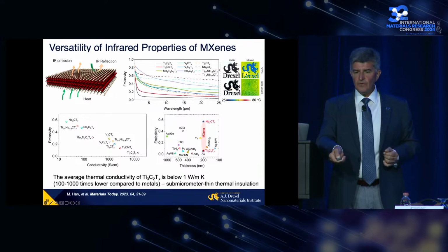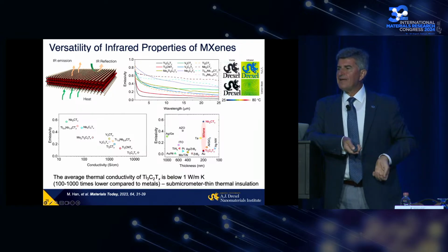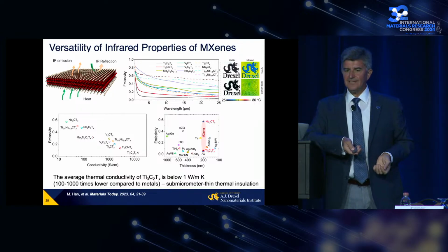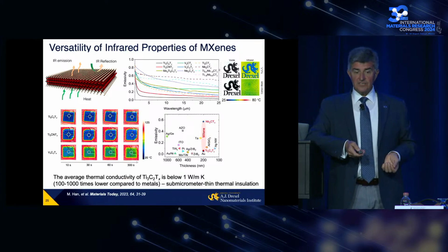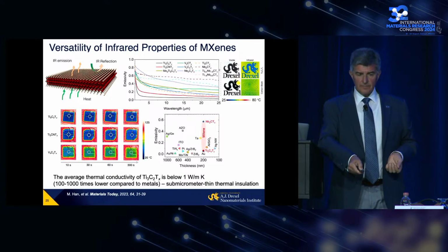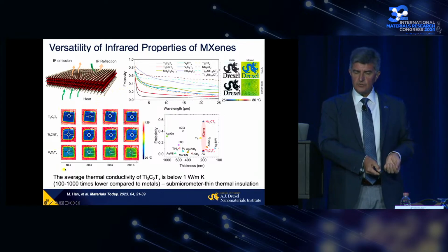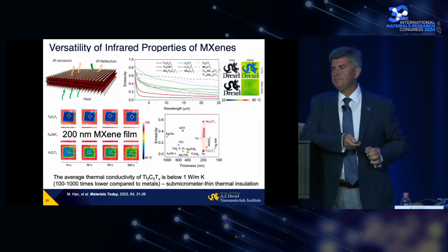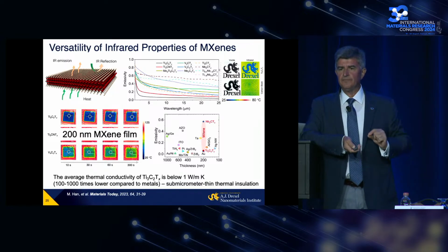You see this one on an 80°C heated hot plate remains cold, there is no emission light here. And this is a glass slide with MXene coatings, 3 different MXenes. You see they behave really differently, and you can see it from this plot, placed on a 120° hot plate. This film is 200 nanometers, and we get about 90 or 100 degree temperature drop on a 200 nanometer film.